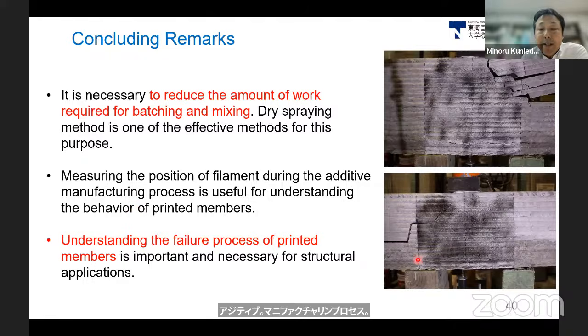applications. And this right photo shows the crack pattern in the shear failure. Of course, even in the shear failure case, the crack pattern is very complex, sometimes following the interlayer of the printed layers. So we should have much more data related to the fracture process of the concrete members.